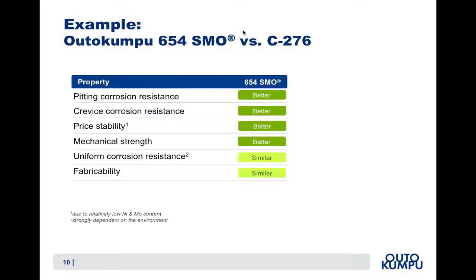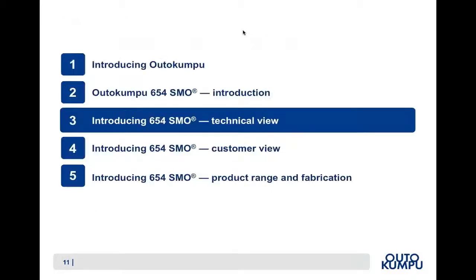If we compare 654 SMO with the nickel alloy C276, we can see that across the major criteria of pitting and crevice corrosion and mechanical strength, 654 SMO is superior. In uniform corrosion resistance, depending on the environment, it should be similar, as is fabricability. But due to the much lower reliance on nickel, the price stability of 654 SMO is superior, as it's not so much at the mercy of the volatility of the alloy price.